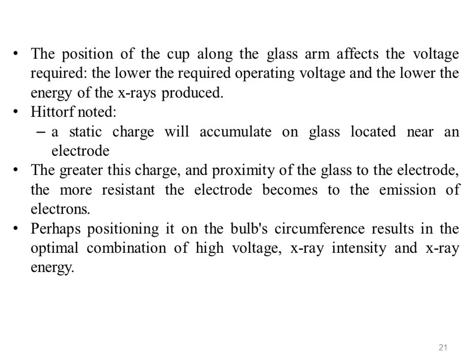The reason, as Hittorf noted, is that a static charge will accumulate on glass, meaning the glass arm located near an electrode. The greater this charge and proximity of the glass to the electrode, the more resistant the electrode becomes to the emission of the electrons. Perhaps positioning it on the bulb circumference results in the optimal combination of high voltage, X-ray intensity and X-ray energy.